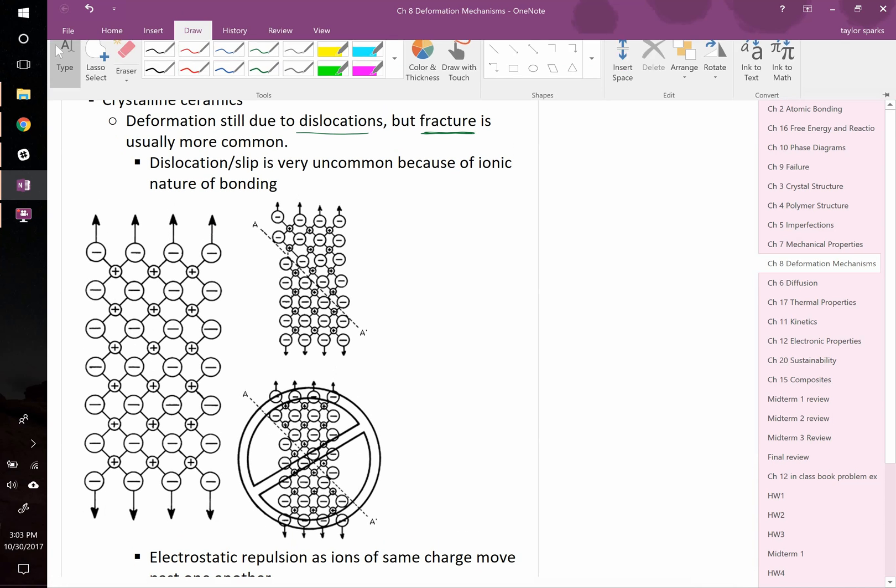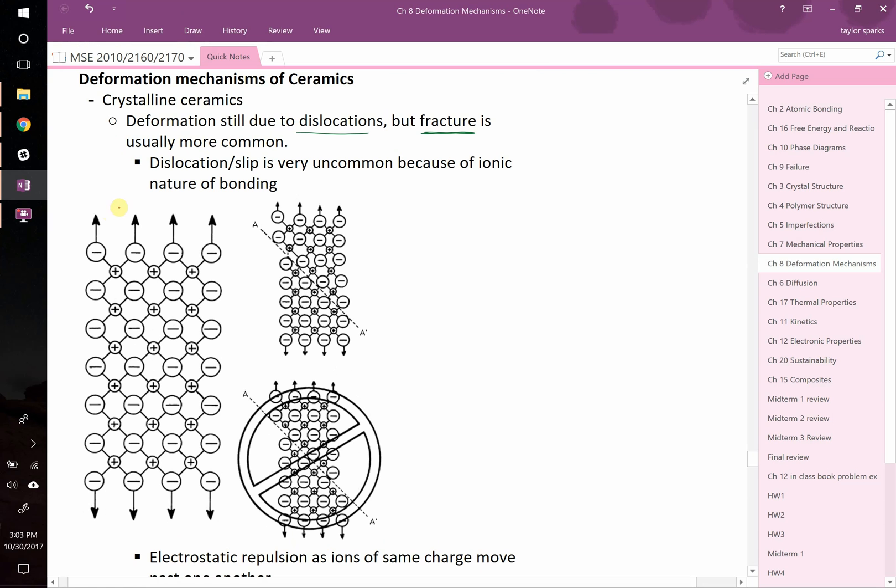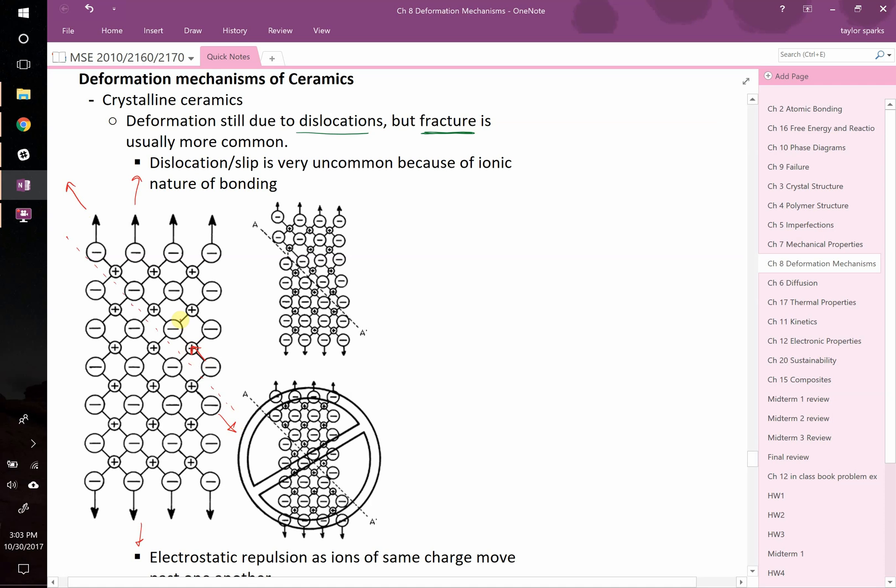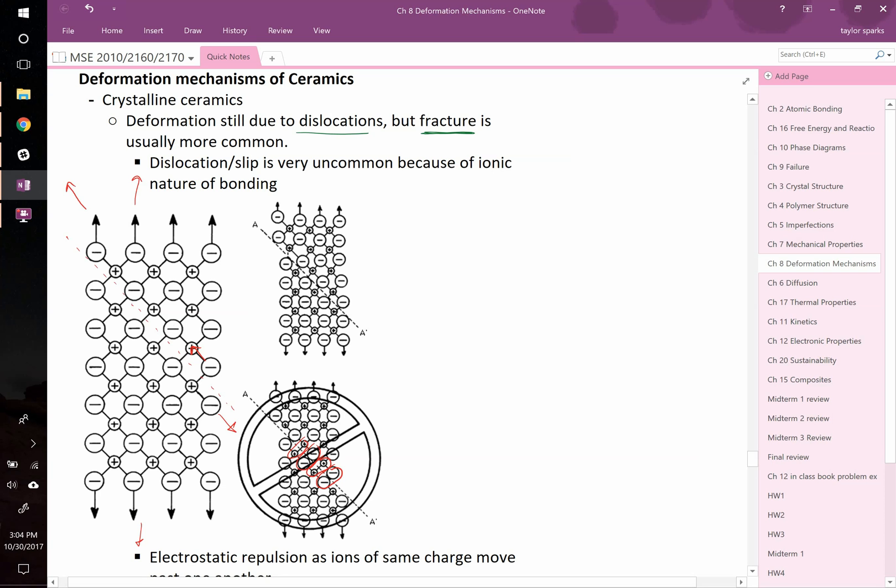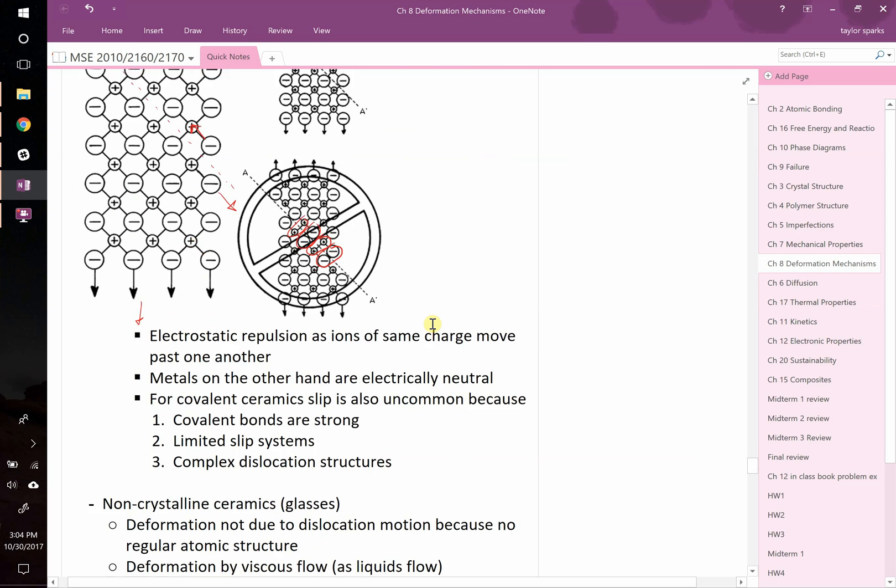The reason this is more commonly occurring has to do with the structure of ceramics. If you look at what's happening in the ceramic structure, take a plane like this one here. That's a high-density plane. If you're pulling on this thing, why won't it just shear in that direction like it would with a single crystal? The challenge is that if it was going to shear as these atoms slide upwards, the negatives are going to have to slide past the negatives, positives past positives. You're going to generate extremely large electrostatic repulsions. You're going to have to cost so much energy in terms of electrostatic repulsion that it's cheaper in terms of energy to just fracture and create two new surfaces that have a surface energy associated with them. That's why most of the time ceramics don't do much plastic deformation.